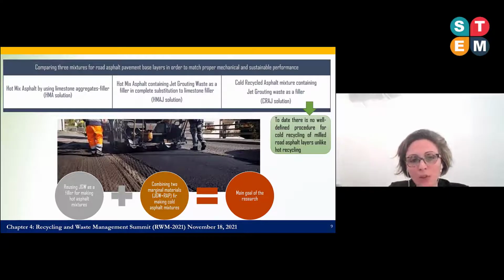The main goal of this presentation is to compare 3 asphalt mixtures for road asphalt pavement base layer that match standard requirements, in particular specific technical requirements in southern Italy. We compared 3 main solutions. The first concerned hot mix asphalt using limestone aggregates and filler. The second refers to hot mix asphalt containing jet grouting waste in complete substitution of natural limestone filler, compared to the grading curve of the previous mixtures. And the third refers to the cold recycling of milled asphalt pavements, adding jet grouting waste as a filler. The jet grouting waste was ground and sieved for its reuse, while reclaimed asphalt pavement was used as it is, as a result of the milling process.